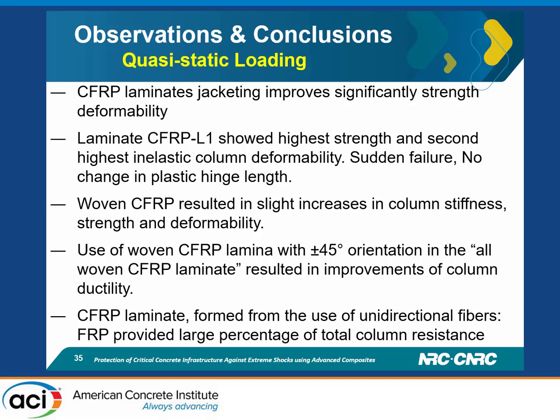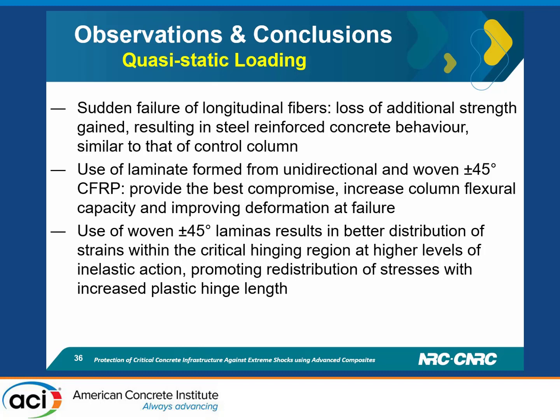And then I will go forward to the quasi-static. In the quasi-static, the failure mode is very similar to the blast failure. When you apply a very high-speed load, or a uniform distributed load in the case of the shock tube, and when you use the quasi-static mode of loading, they give exactly the same failure. However, the effect of the high strain rate shows when you compare with, for example, the U.S. Army standards or other standards for blast design. It makes a lot of sense to use amplification factors for the material and the level of strain rate that we are using.